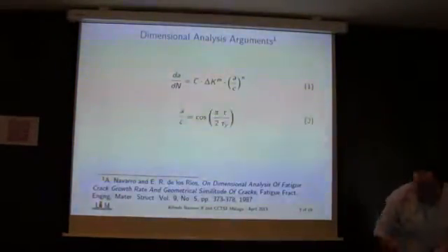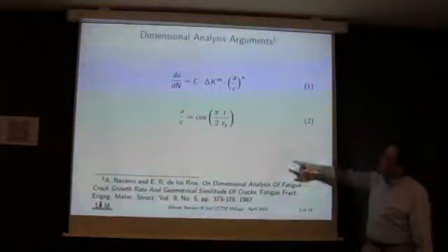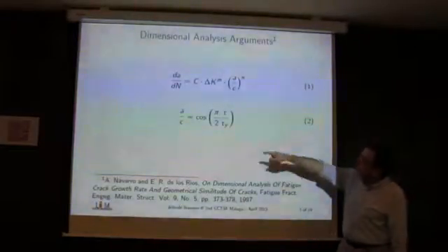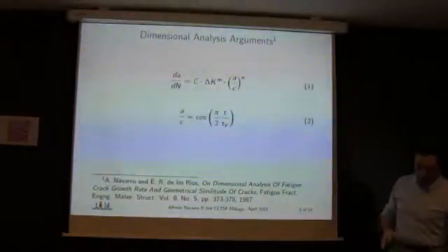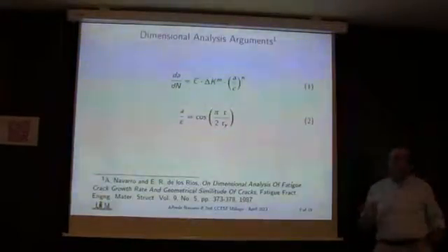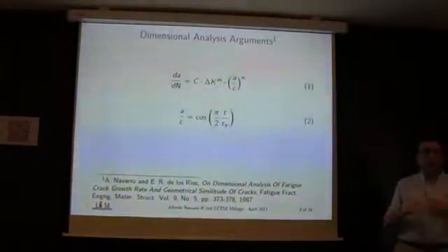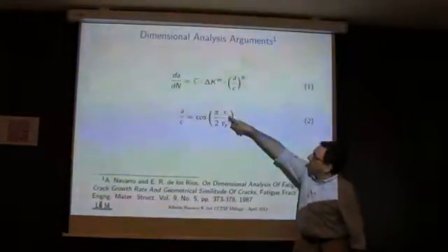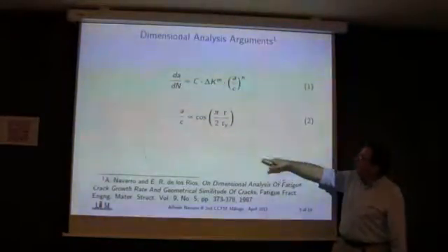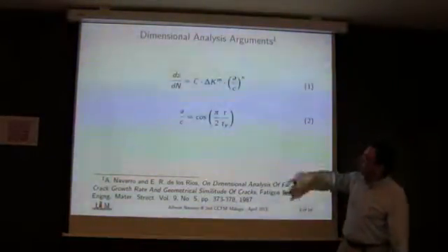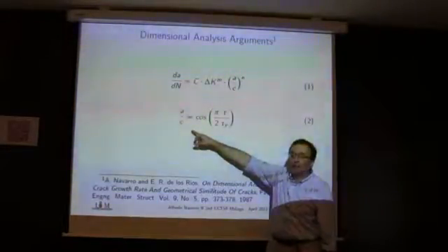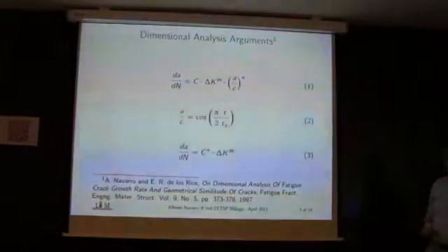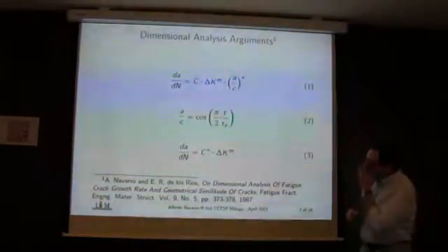But if you think in terms of the Dugdale relationship, this relation between the two lengths is connected to the applied stress and perhaps the yield stress. When you are dealing with low cyclic loads, sufficiently low to apply linear elastic fracture mechanics, it turns out that this ratio here is below 0.3, and then the Dugdale relation says that this is approximately between 0.9 and 1. So in this case, you really have the Paris law, right? This is something which is quite well known.